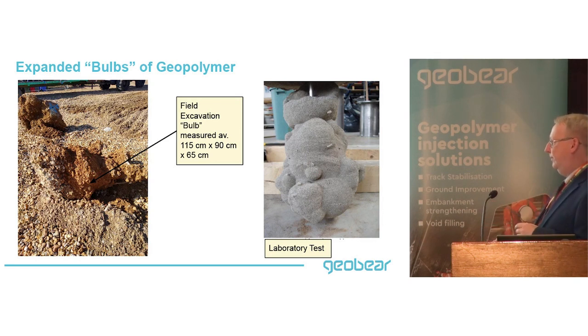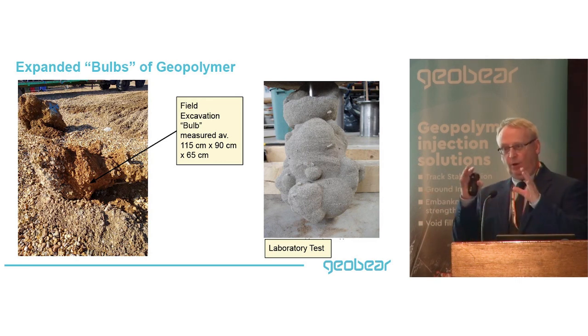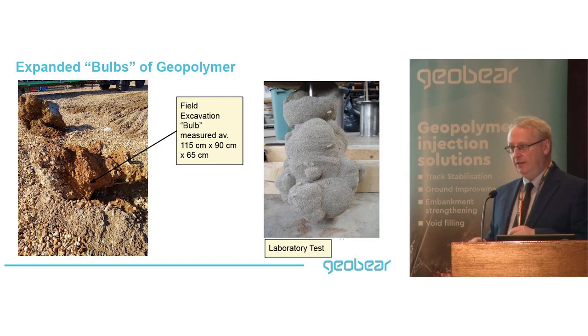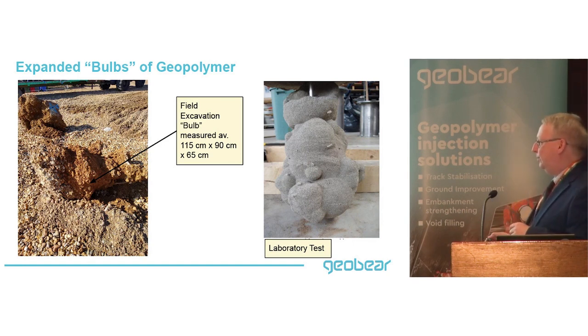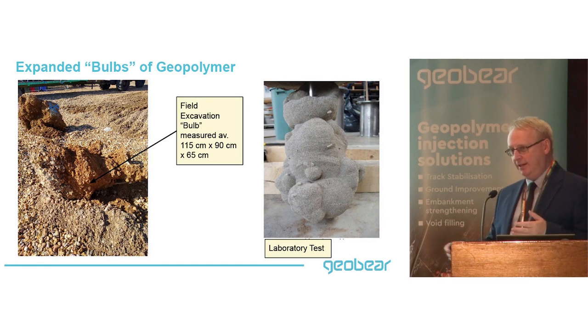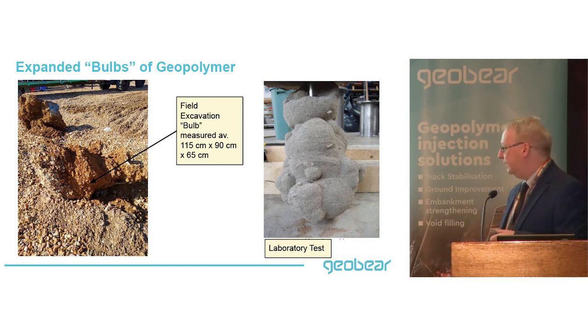So it's a big lump of gravel and polymer mixed together because the polymer is actually in between the gravel - it's a bit like concrete. When you cut this stuff open, you can see polymer and gravel all mixed together. So you get these large bulbs forming, and the size of the bulb is proportionate to how much you put in and the depth at which you inject it.